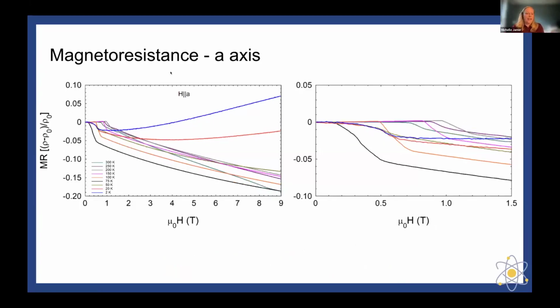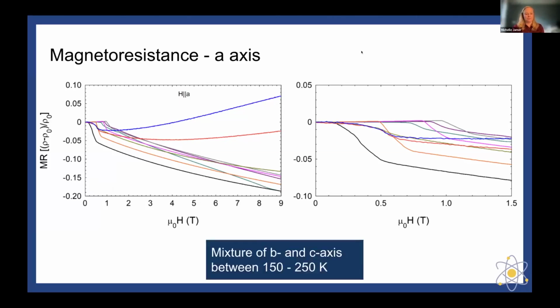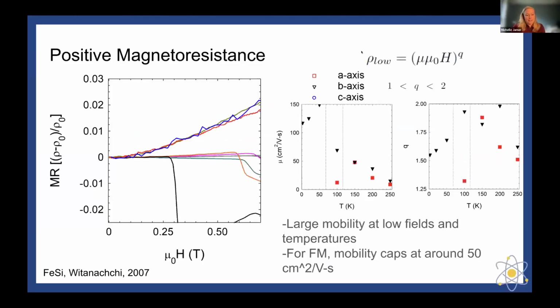And then if we were to take a look at the A-axis, it is actually a little bit of a mixture of the B and the C, where we do see that suppression at low temperatures before the material enters the helical spin spiral state. And then whenever it enters the helical spin spiral state, we actually do see a positive magnetoresistance that scales similarly to the B-axis. So the positive magnetoresistance is one of the big things to take away from this talk, which is kind of rare in a lot of these antiferromagnetic materials because it's related to a super large mobility.